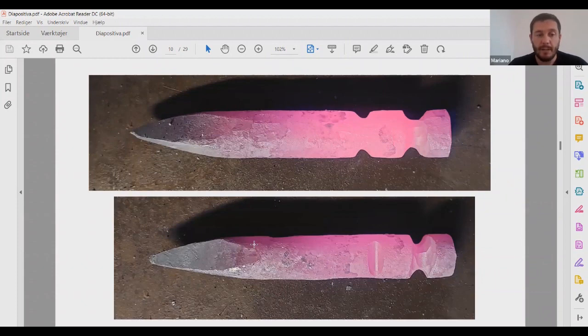The next step will be to turn the piece 180 degrees and forge the other end. We can use a hammer or some type of tool such as a guillotine or similar. We will seek to separate the spike from the blade and approach the shape of the bolster. From this, we will forge 4 sides for the tang and only 2 to generate the neck of the blade. Ideally, we use a guillotine tool with a radius of approximately 8 to 12.